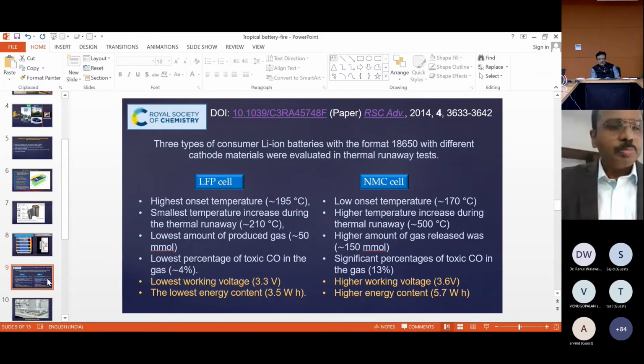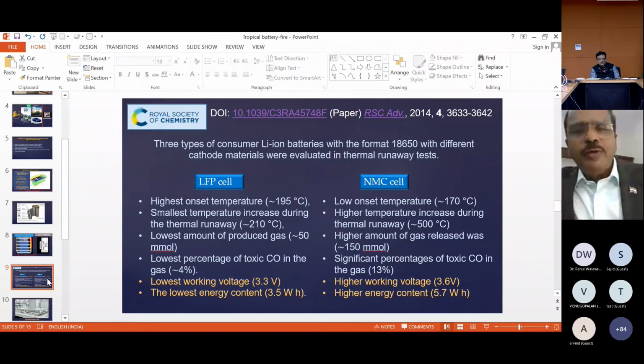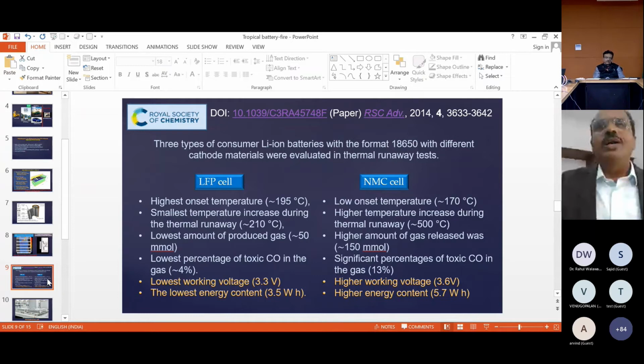So 3 types of consumer lithium-ion batteries in the 18650 format with different cathode materials were evaluated in this paper, Royal Society, just to show what kind of reactions and what kind of consequences happen; they did it under controlled conditions. As they increase the temperature, the onset temperature for LFP is 195 while NMC is 170. That means it is a much lower temperature at which it starts heating up, and the smallest temperature increase during the thermal runaway is 210 only, while for NMC it is 500.